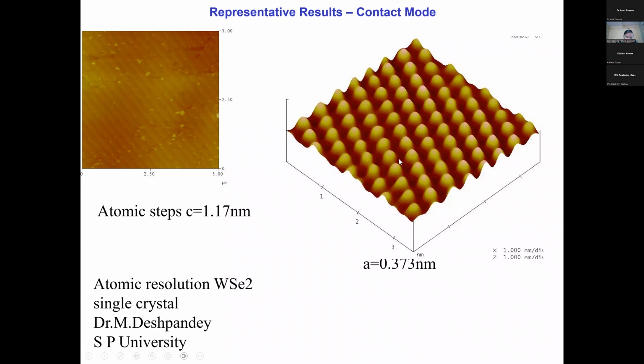Tungsten atom or selenium atom is very difficult to distinguish in the AFM. Very, very difficult. Therefore, STM will be very useful because tungsten is metallic and selenium is non-metallic, and with application of positive bias, you will see the tungsten. With application of negative bias, you will see selenium, etc. That can be studied. That's why scanning tunneling microscopy is a far better tool here. Otherwise, at least up to the level that you can go, that is what structures you can see.